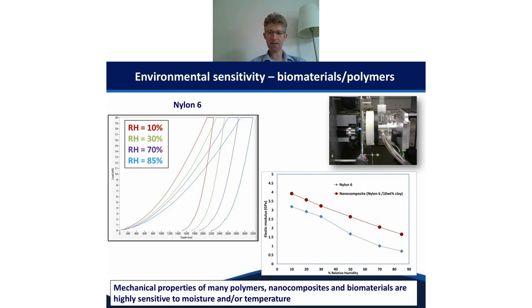And they've done that with this little humidity chamber here, which my colleague Adrian designed. It works very, very nicely. It just sits in the nanotest system, and it allows us to very rapidly control that test environment, so rapidly change the humidity in the environment and then do tests rapidly.